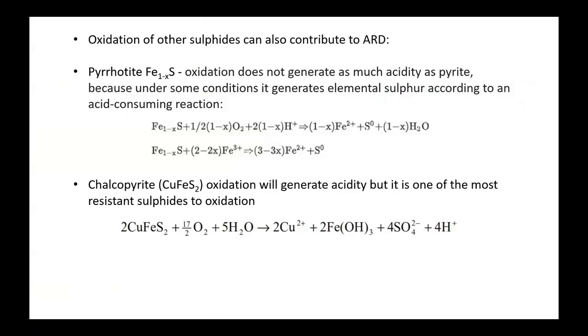Next slide, sorry. Okay, other sulfides. So there are other sulfides that can contribute to acid rock drainage, but really they're not as significant as pyrite. Pyrrhotite does oxidise and does form acidity, but it frequently generates elemental sulphur. And if it precipitates in that way, it actually uses up acid rather than releasing it. Chalcopyrite will definitely generate acidity, but it's actually not nearly as reactive as pyrite. And as it says there, it's one of the more resistant sulfides to oxidation. Next.